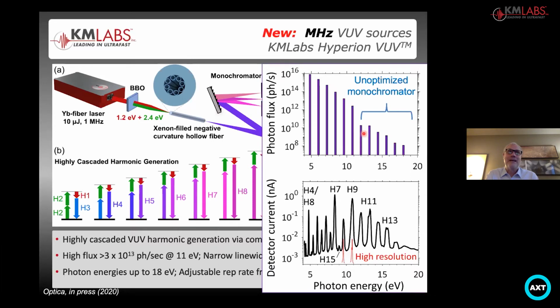Now, this source actually is very promising to use with new types of detectors. So time-resolved ARPES detectors, and there are several types of them out in the market now, are very interesting as a new direction that still has a lot of untapped potential. This is just some examples of what you get from this source. The flux is highest at lower photon energies. It decreases toward high energies, but it's still quite bright even beyond 10 eV. To date, this is very developmental. We've done about 3 of these units so far, and its use in ARPES is as yet untapped.